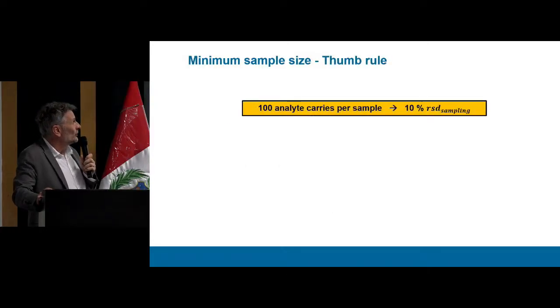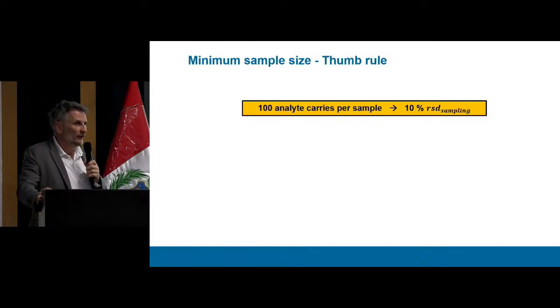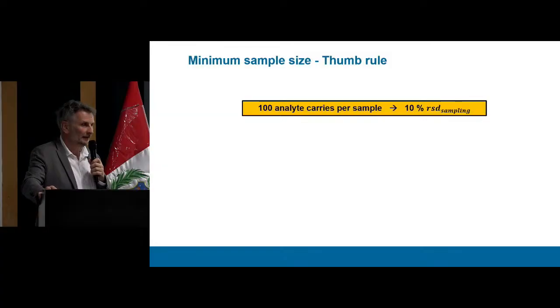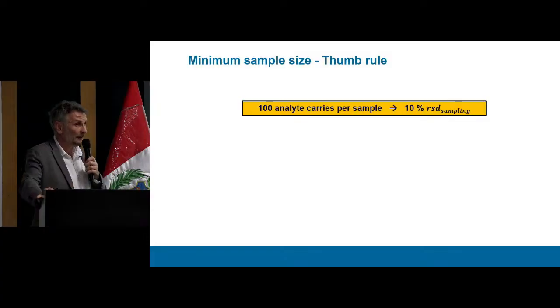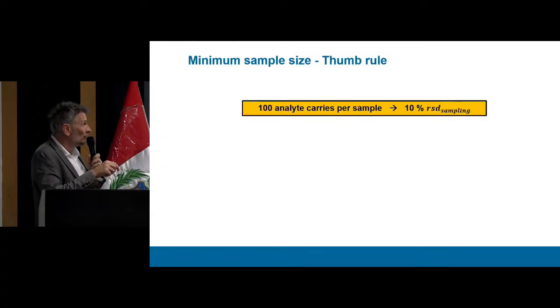There is one thumb rule when we apply sampling. We should find in our sample mass, what we take, about 100 particles we are interested in. Imagine you would like to know the concentration of batteries in our municipal solid waste. Then the correct sample size would be that we find at least 100 batteries inside the sample. If we do so, our final sampling error will be about 10%.